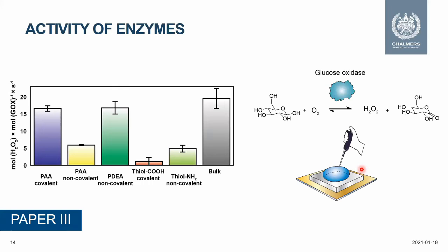We then measured the activity as a function of the bound quantity of enzymes. We observed that a high degree of activity retention is present in polyelectrolyte brushes and that the self-assembled monolayers had very low activity in comparison. In fact, we fully retained the enzyme activity compared to the bulk enzyme solution activity.